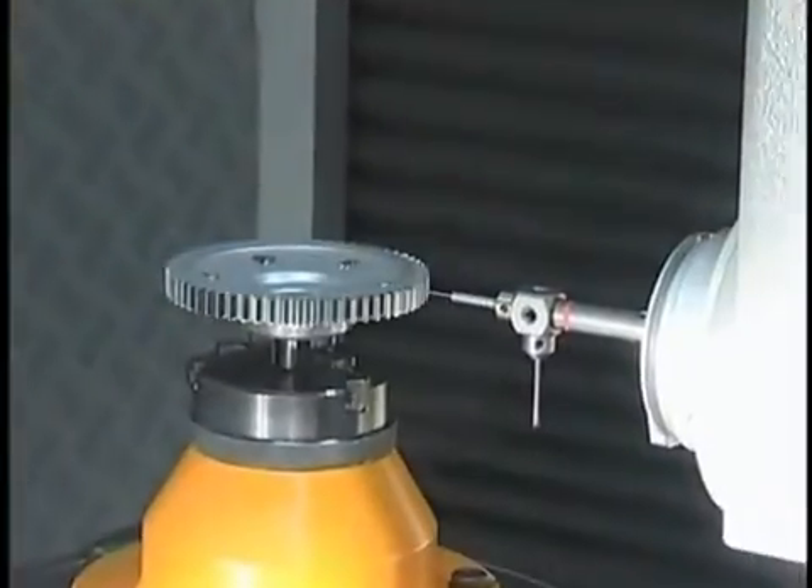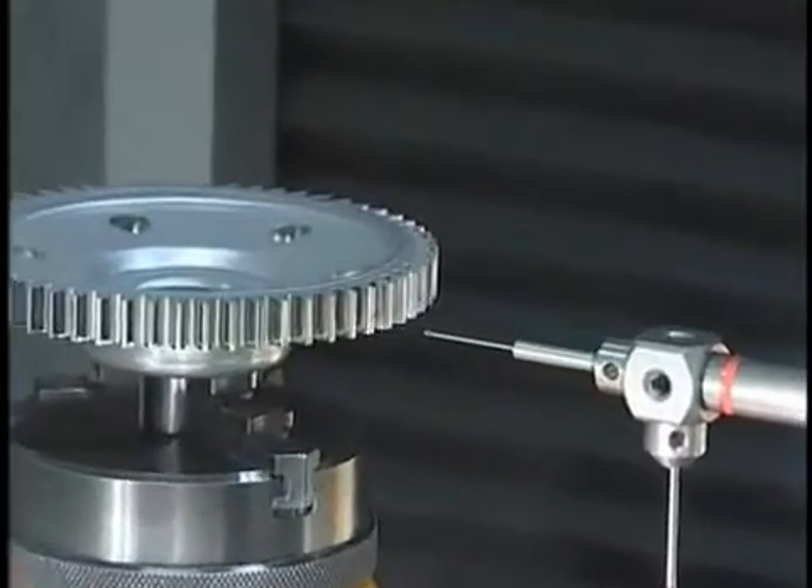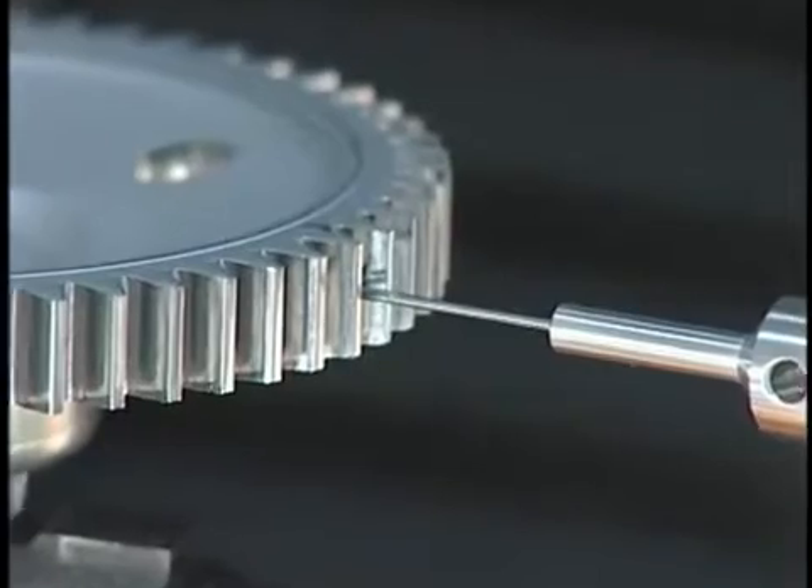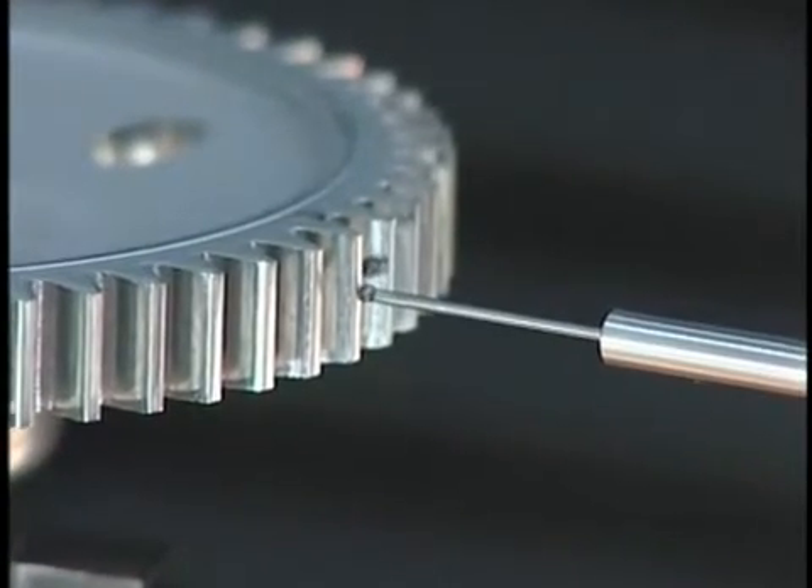Using a pre-alloyed ferro-molybdenum-based steel, the manufacturing steps were coaxial compacting on a multi-platened press, followed by sintering, sizing, case hardening, hard turning, and honing.